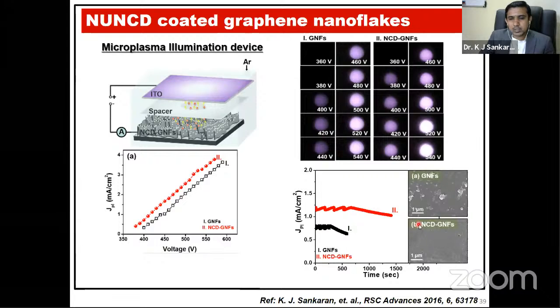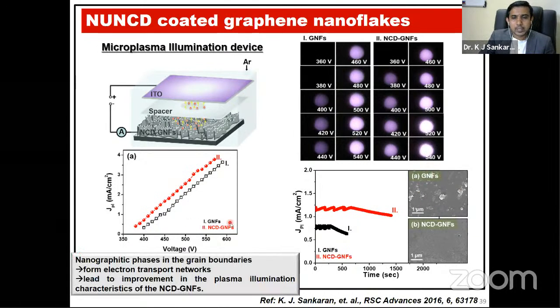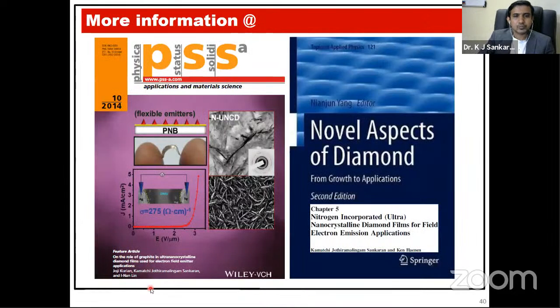But if you see the nanocrystalline diamond coated on the graphene nanoflakes, which can go for more than 1500 seconds, the NCD coated on the graphene nanoflakes is not etched out by this plasma. So this is very stable with a good electron emission as compared to the graphene nanoflakes. Again, the nanographitic phases in the grain boundaries achieve a very good electron transport mechanism, with a good improvement in the plasma illumination characteristics.